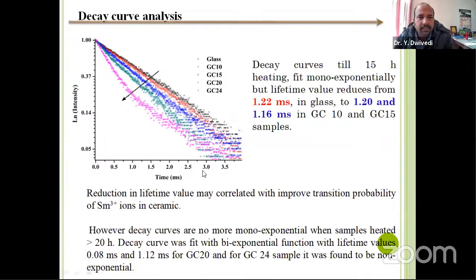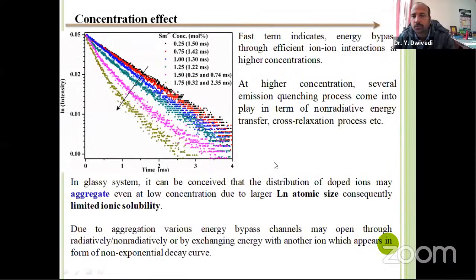So we analyze this decay curve also with respect to the heating hours, and you see after 15 hours of heating, this decay curve is no longer mono-exponential, and a two-lifetime component starts appearing. We further analyzed this with respect to ionic concentration, and you see till 1.25 mole% samarium concentration, beyond that, a bi-exponential fitting appears, and a fast term also appears.